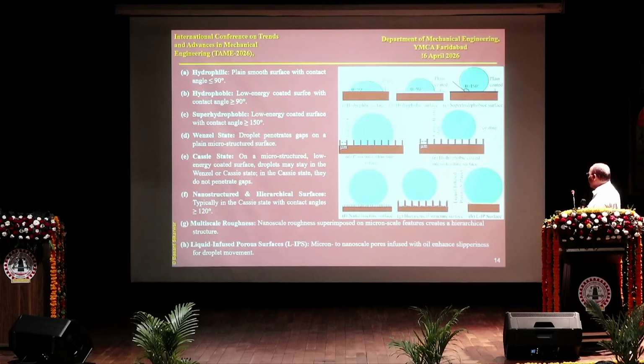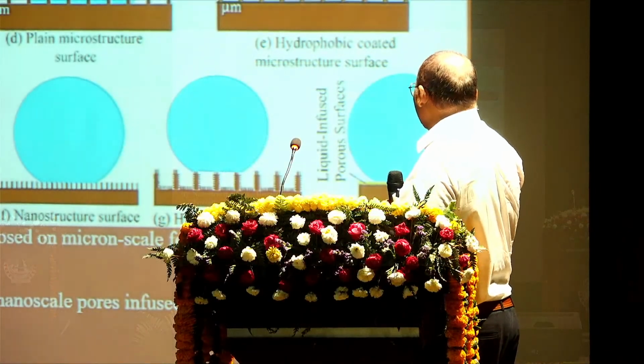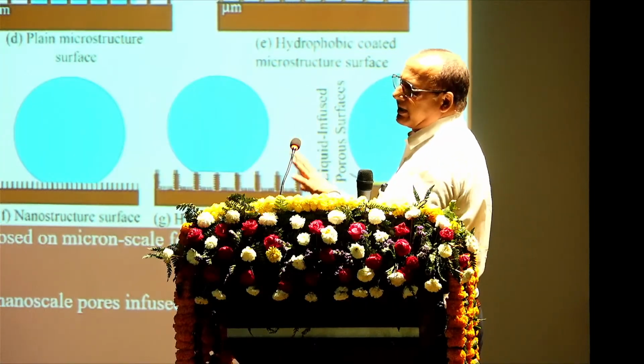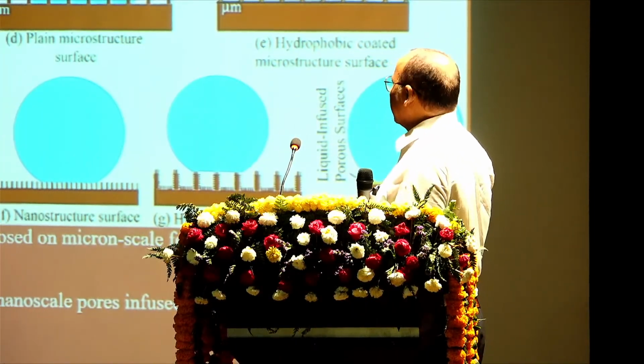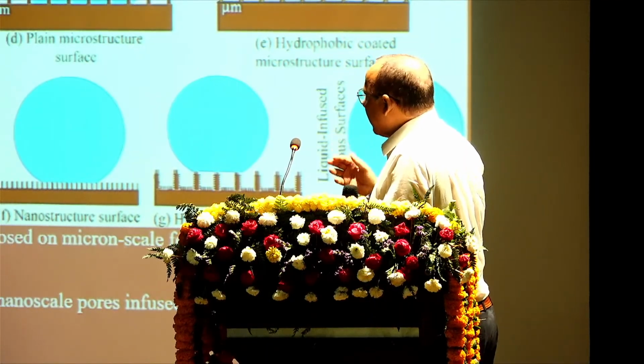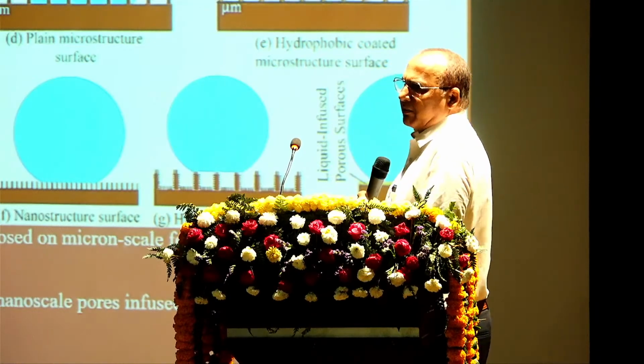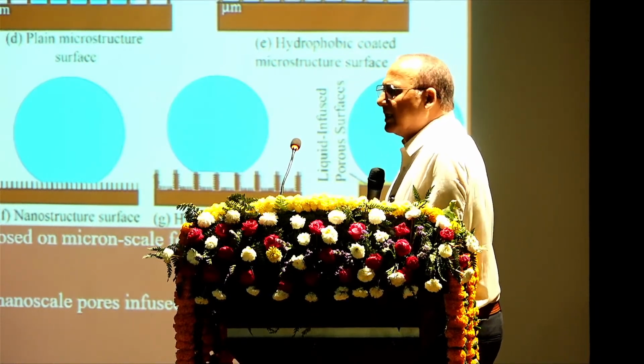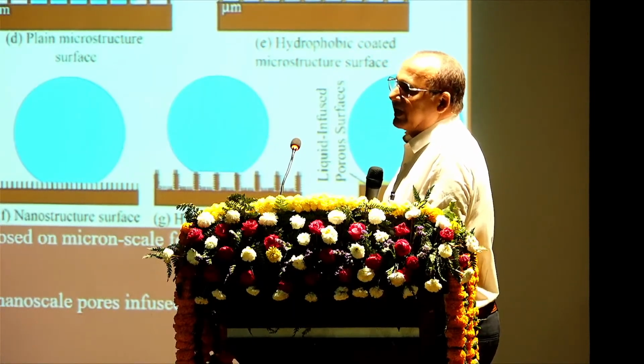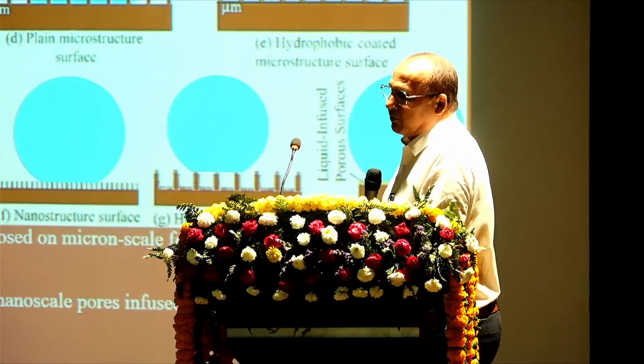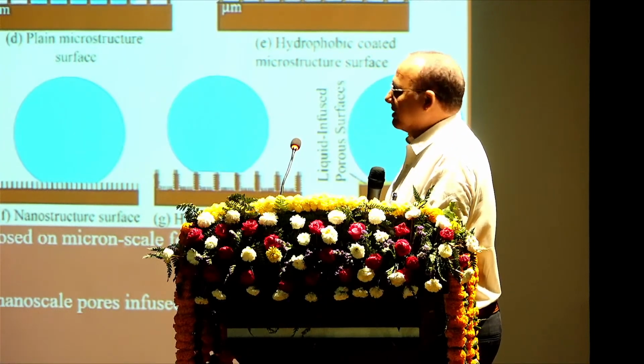Then there is a nanostructure surface, then a hierarchical structure surface, where you have a microstructure and nanostructure, which you can see in the slides here. Then the liquid infused porous surfaces: you form pores on the surface, then you put in a low surface energy liquid, and it becomes a liquid infused porous surface. So these are the surfaces people are trying in the literature, and we also explore many methods to fabricate a super hydrophobic surface. As you know, my target is to enhance the transport coefficient of condensation. So I am only focusing on metallic surfaces like copper and aluminum. These are the two surfaces which are more and more popular for use in energy systems. Next slide.